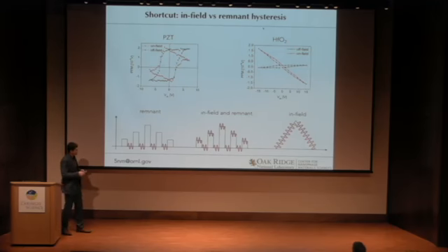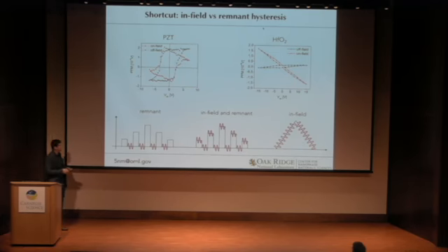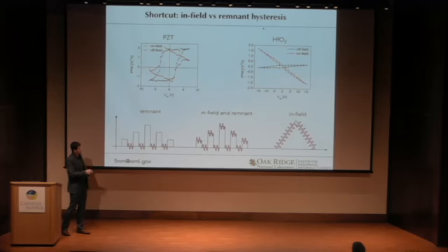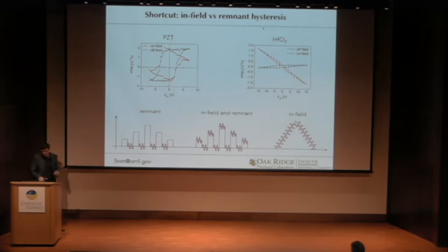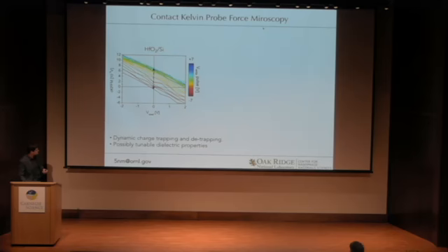So basically imagine measuring piezo response here on top of these and here, and then comparing them against each other also reveals a very dramatic difference between the two types of hysteresis, which looks weakly dependent on the procedure in PZT and very dramatically electrostatic in-field, whereas some weak response in the remnant response. So we can pretty much very clearly differentiate with this protocol or with this approach, or looking at the in-field variables, something that's ferroelectric from something that's not.